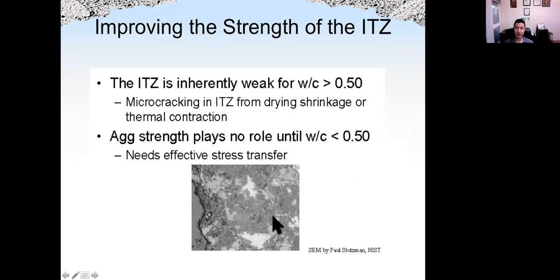So that is cement paste. And then let's look at the ITZ, which is the boundary between the cement paste and the aggregate. The ITZ is typically weaker if the water cement ratio is high, higher than 0.5, then we could have micro cracking in the ITZ due to drying shrinkage or thermal contraction. So here it says aggregate plays no role until the water cement ratio is less than 0.5.